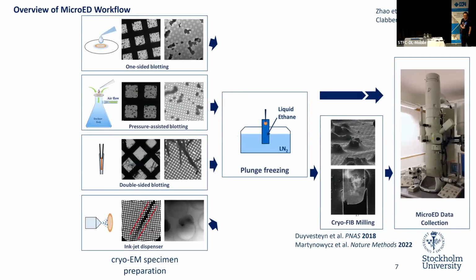And because we're collecting data in a TEM, in order to have an electron beam, we have to have a relatively high vacuum environment. This means we have to prepare the sample in a similar way as cryo-EM people do, right? To vitrify the sample so that the crystal is not destroyed by the vacuum. And there are several ways to do it. And actually, it's not so difficult anymore that you can do pretty much each one of them and then just vitrify the protein crystal and put it into the TEM. And then if the crystal size is suitable, we can put it into a microscope directly to measure.